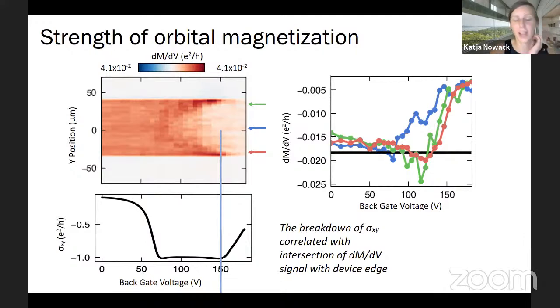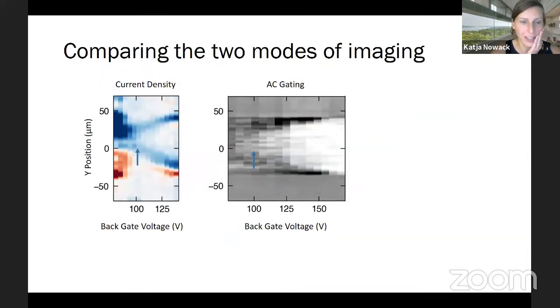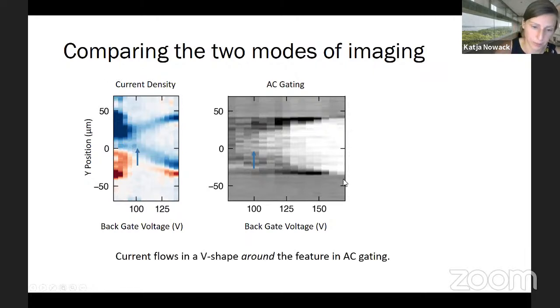All right, so we think we have some good understanding of what we're imaging here. And it's worthwhile to point out that if you compare the AC gating data, so the data where we modulate the top gate of the device, and compare that to the images of the current density, this clear V shape shows up in both of them. And it appears that the current really seems to be avoiding or flowing around the V shape that we see in the AC gating.